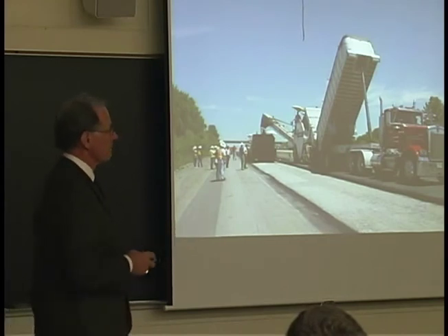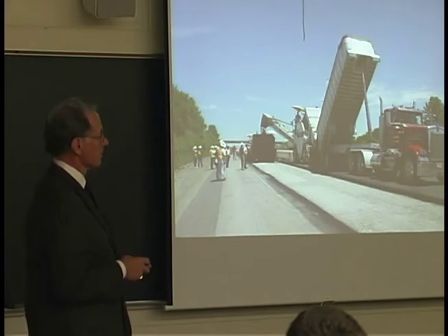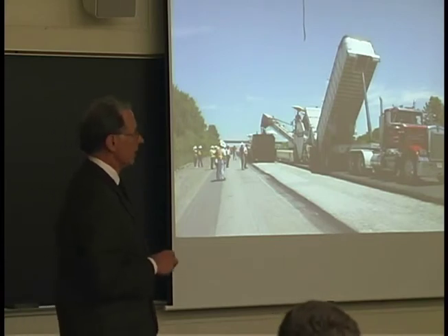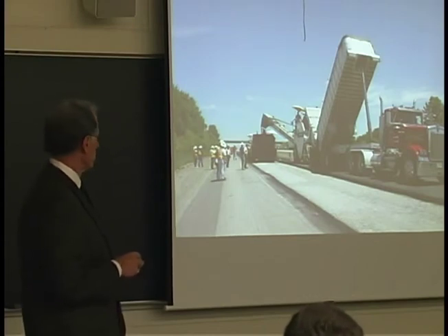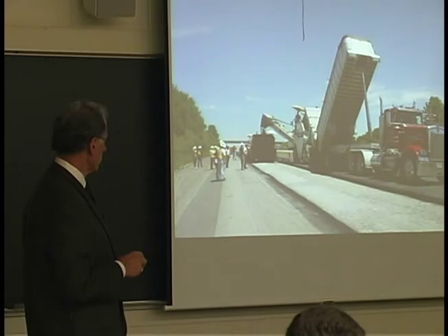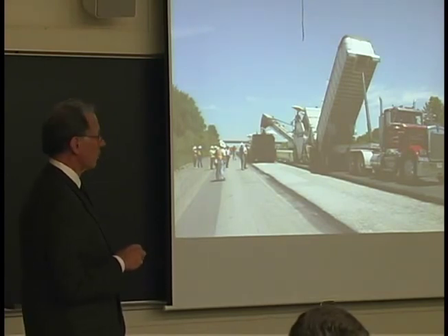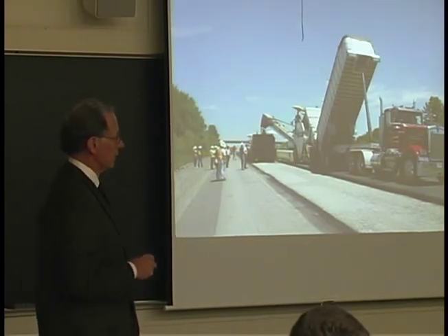Just roughly, what are the layers from the soil to the finished product? How many layers do we have? On Interstate 70, we put about 17 inches of asphalt. The first lift was 6 inches thick, and then we went up in various thicknesses of probably another 4 and a 4, and then probably 2, 2, and on up to the top.